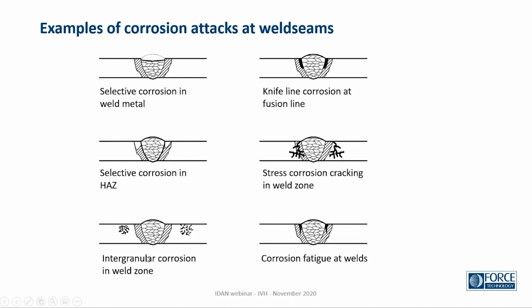We could have what's called intergranular corrosion, which is corrosion around the grain boundaries in the metal caused by the heat from the welding, and it would often be a little away from the fusion line compared to the heat affected zone. Some metals could cause knife line corrosion, which is sort of a HAZ problem, but only along the fusion line. In low alloyed steel, it would be related to too much sulfur in the material, and in some stainless steel with titanium or niobium, it could be something about the carbides dissolving and forming during the welding process.